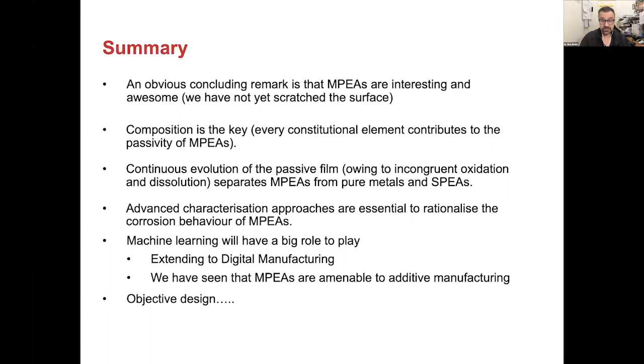Composition is key. So talking about corrosion, composition is key because every constitutional element contributes to the passivity of these particular alloys. Even though many of them are passive, in fact, most of them are passive, they have a different underlying or a different kinetic mechanism to that passivity. There's a continuous evolution of the passive film that's coming from incongruent oxidation and dissolution, which separates MPEAs from pure metals and single principal element alloys. And therefore, that's why advanced characterization approaches are actually essential to understanding the corrosion behavior of multi-principal element alloys.